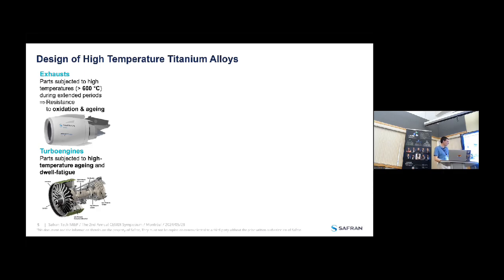Or we're talking about in-engine application, basically the high pressure compressor discs that are subjected to very high level of mechanical loads due to high rotational speeds, for example. And the context of this study was actually to find a titanium-based alloy that was less sensitive to a particular form of fatigue, which is dwell fatigue, which leads to very premature rupture of the disc that caused an incident a few years ago.